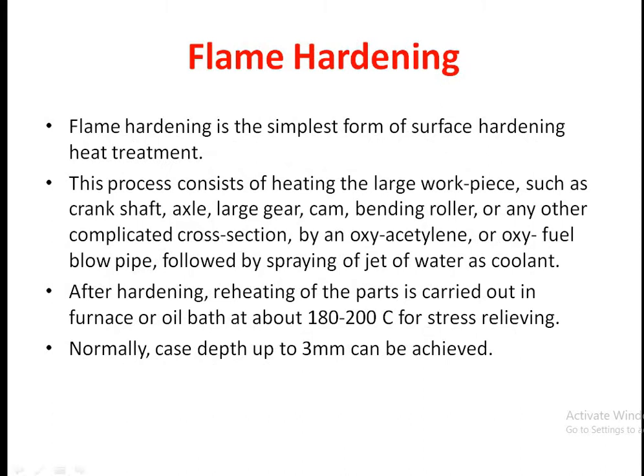Flame hardening is the simplest form of surface hardening heat treatment. Using a simple torch — such as an oxyacetylene or oxyfuel blowpipe — large work pieces such as crankshafts, gears, cams, or complicated cross-sections are heated. This is followed immediately by spraying a jet of water as a coolant.